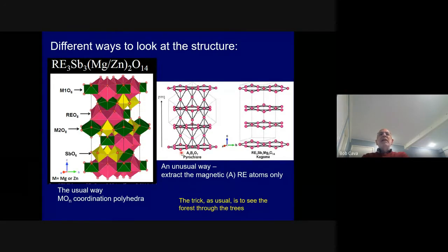And then you can see that if you could make this with the same rare earths, you can make an A2B2O7 pyrochlore and make an A3Sb3Mg2O14 Kagome. And if you just look at the magnetic sites, you can clearly see that this one is a pyrochlore made of corner sharing tetrahedra. Here's two of them. And this one is a Kagome. Okay. So the trick is always to see the forest through the trees. Let's see, can we get the next slide?